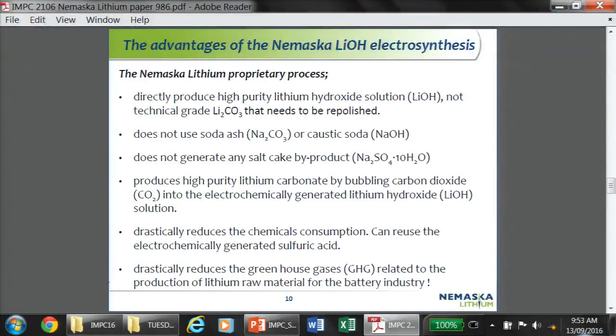And the advantage compared to the conventional process, when you add the soda ash, even if you purify the lithium sulfate and even if you purchase the highest grade of soda ash, which is a high cost, you need to repolish your lithium carbonate, because when you add the soda ash to your lithium sulfate solution, you add impurity. So from lithium sulfate to lithium hydroxide, you need to produce carbonate first, repolish your carbonate, and after that reconvert your carbonate into hydroxide. So that's two different chemical processes with polishing. That's why it's really an advantage to directly produce lithium hydroxide.